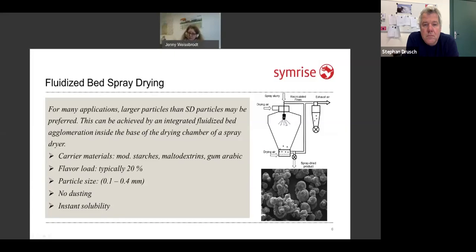They come in contact with a nebulized slurry here. This is where the particles get partly wetted on the surface, and then on their way down during their drying in the drying chamber, they come into contact and stick together because of this partly wetted, sticky surface. They will dry and can be harvested as final agglomerate particles. These particles have a very loose structure, and this is what is really aimed at in this process, because these loose agglomerates have an instant solubility.